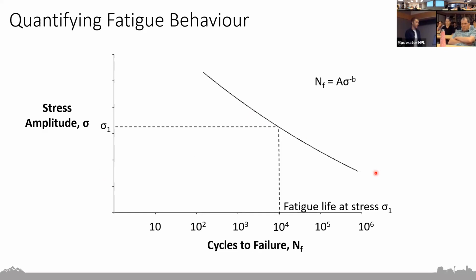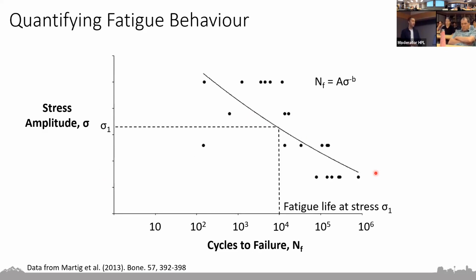The relationship is typically pretty nicely represented with an inverse power law. But when we look a little bit closer at some of the underlying data, we see there's actually a pretty significant amount of scatter. And this happens even when samples appear identical in macrostructure and they're loaded to the same magnitude. We see this scatter span two and even three orders of magnitude. So given that we see this scatter even when we hold all these extrinsic loading parameters constant, it leads us to believe that it's a result of the inherent variability in the bone microarchitecture.